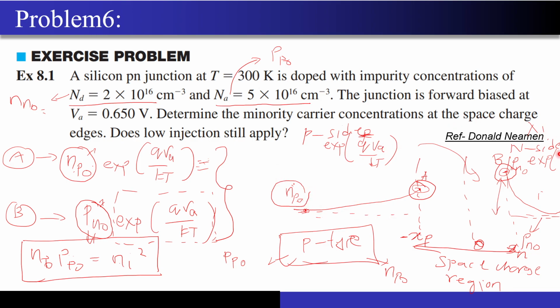Of course, this is a composite semiconductor material. I have a p side, I have an n side, I have a depletion region, right? But you may have heard that in the region far away from the depletion region, you generally don't have an electric field. Like in the last lecture, maybe the recombination and generation current lecture, some may have mentioned that a finite amount of electric field is there, but that is very small actually, right? So if the part of that semiconductor material that I am considering is under equilibrium, there I don't have a concept of quasi Fermi levels. That is what we generally say.